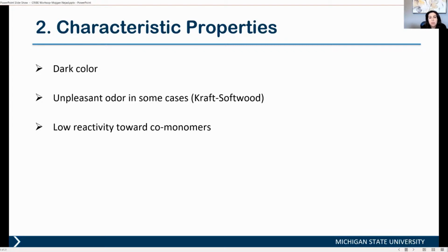In most cases, because we are dealing with natural polymers with very complex structures, we have a problem with the reactivity of lignin toward co-monomers. That's why, when choosing lignin to replace petroleum-based chemicals, it's very important to measure the reactivity of lignin with co-monomers. Some of the examples I'm going to discuss today are the reactivity of lignin with formaldehyde, with isocyanate, or with epichlorohydrin. Low reactivity of lignin is a challenge, and we need to choose lignin that has higher reactivity with these co-monomers.